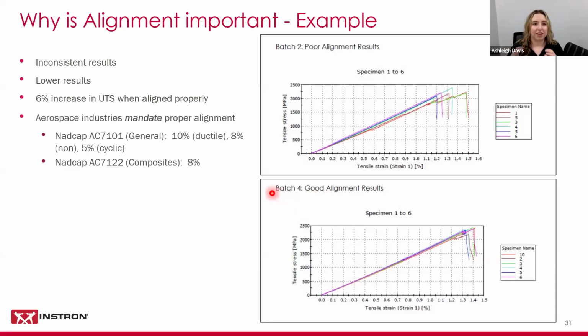We can clearly see in the upper graph that there's a lot of inconsistency. We have essentially some rough stress strain curves and a wide distribution. In our lower graph, we can see that we have less distribution throughout the curves. They're much cleaner. And we actually had a 6% increase in ultimate tensile strength when we did the alignment properly. This might sound like a small number, but that could be the difference in quality control environments that allow shipments or even getting business versus a competitor.